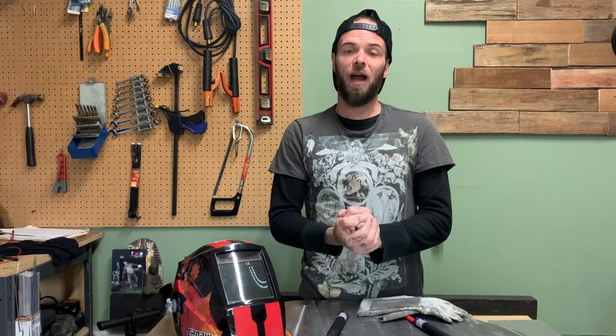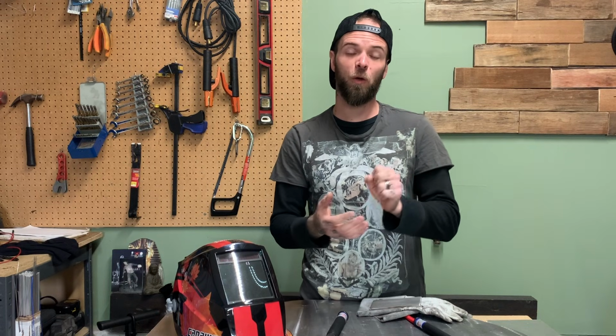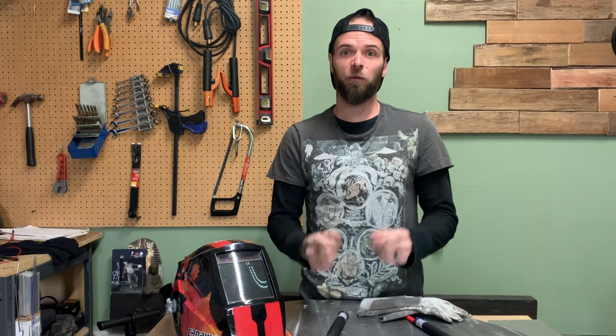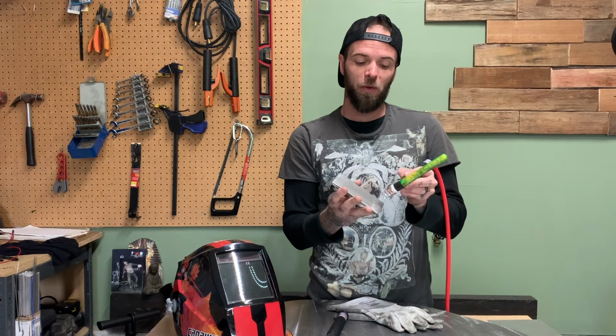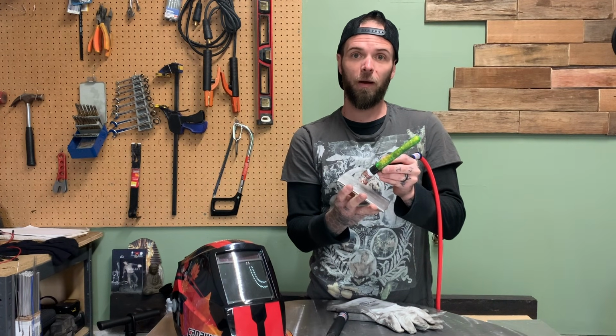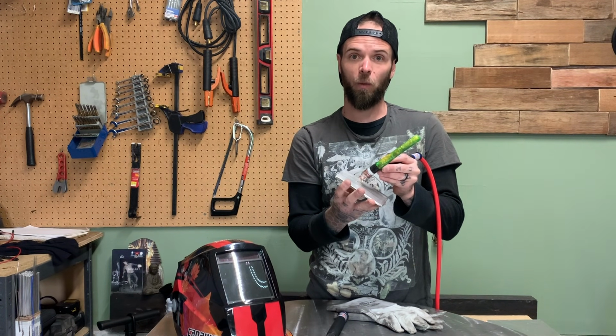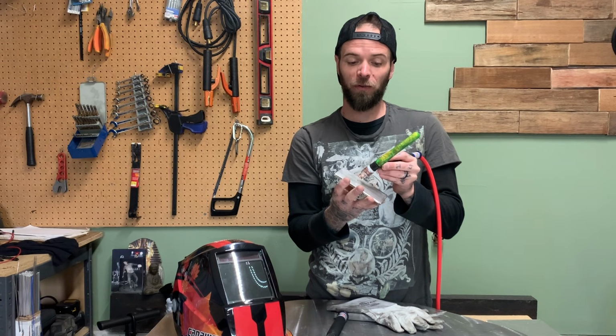So what's basically happening is that the argon shielding has been cut off before the material has finished cooling to a point where it's not going to oxidize. So that change of color real quick is basically oxide forming because all of a sudden the argon cloud has been removed. What you want to do is when you run your weld, you want to make sure that you extinguish your arc and you keep your torch covering the weld. What's happening here is the post flow is going to be running.